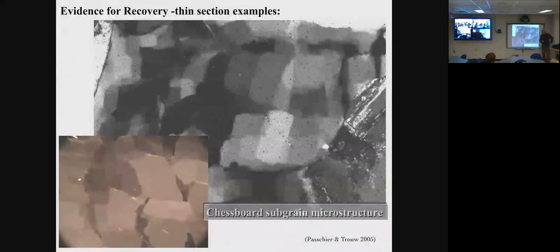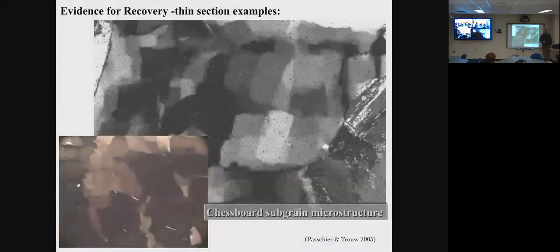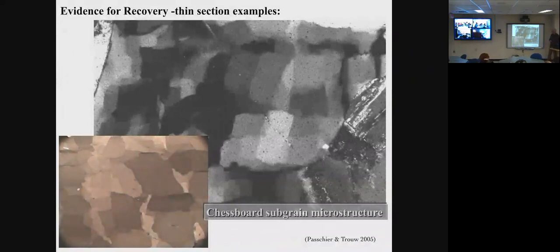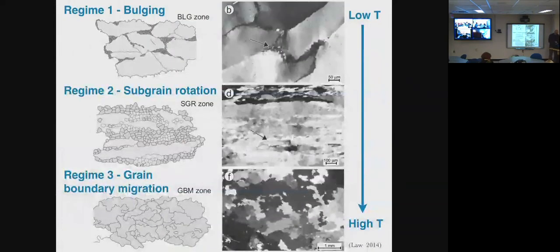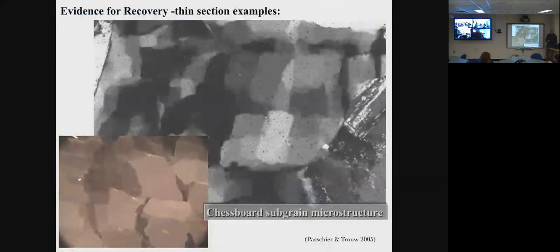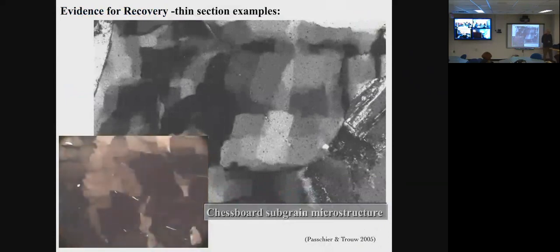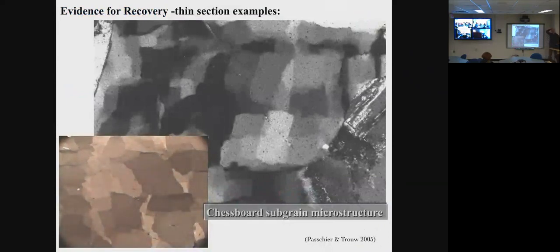Okay, the last type of texture is a highly evolved recrystallization texture that's called chessboard texture. Very similar to subgrain boundaries, but what you see in this diagram here are very clear subgrain boundaries, almost orthogonal to each other. Okay, this is a texture that operates usually at about 620 to 650 degrees Celsius. It's another recovery texture that is produced by dislocations being highly mobile, being very high temperature in terms of deformation. Okay.